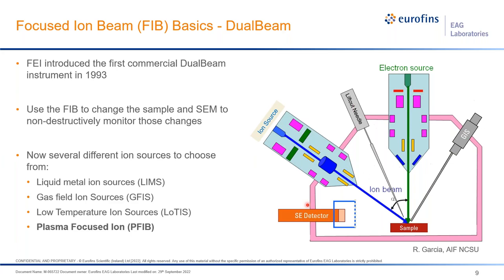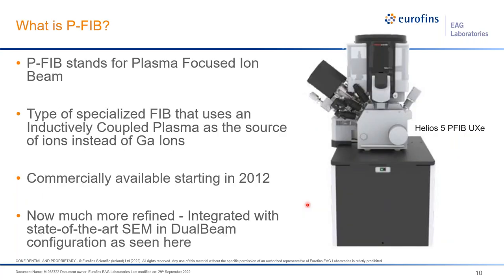So in an effort to further optimize the FIB ion sample interactions, there's actually been a lot of work on developing a variety of different ion sources in recent years. Each of these ion sources then provides control over various aspects of the ion sample interactions that we can't otherwise control with instrument settings, things like accelerating voltage and beam current. So there are inherent interactions between ions and the sample chemically that you can't really overcome. And so in this case, maybe we're going to use something like xenon, which is an inert gas, to do this work versus gallium. And so with that, we introduce P-FIB.